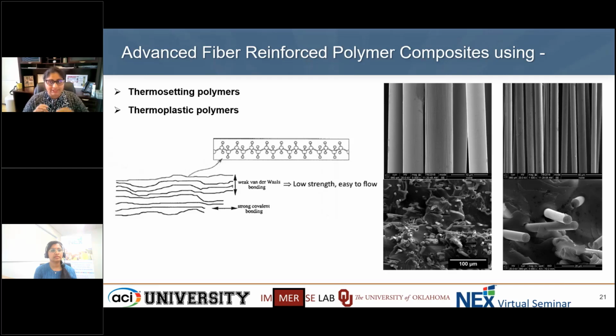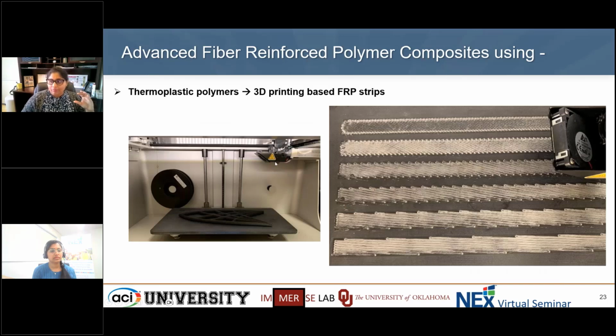3D printing is one of the ways, but it's a very good way because you have so much control on this polymeric resin. So in 3D printing, what happens is they use these filaments of thermoplastic, and the nozzle itself, which is right here, this is the print head and this is the nozzle. That nozzle heats up to, for example, nylon, about 270 C. What that does is it enables sliding of the polymeric chains with each other, and that is why the polymer goes from a hardened state into a molten state.